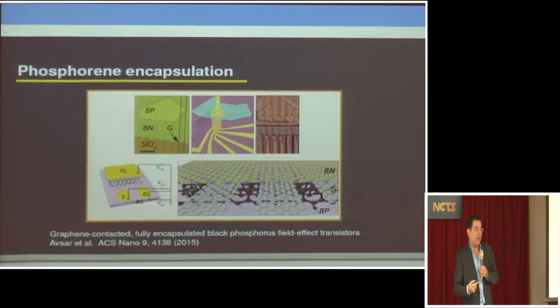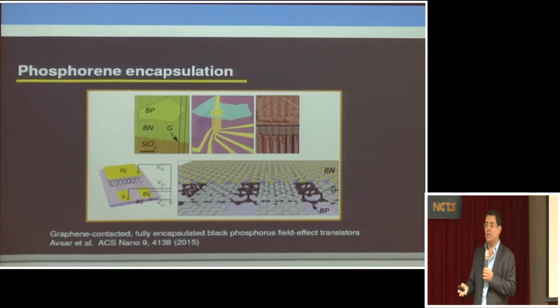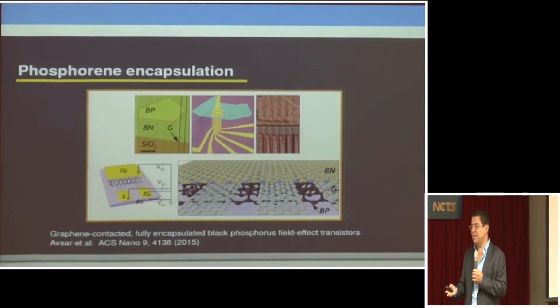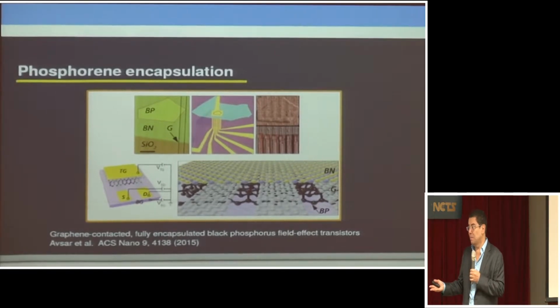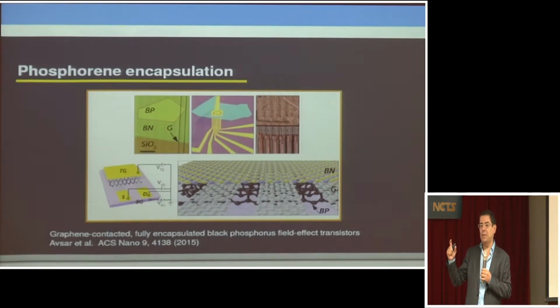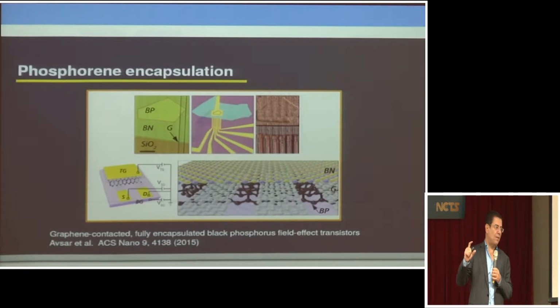So how did we manage to control it? I told you, graphene doesn't oxidize. So the solution is essentially you just cover the surface of phosphorene with graphene. This is called encapsulation. Actually, we don't use graphene most of the time, only when we want to make electrical contact. What we use is a different material called boron nitride, which is a wide bandgap semiconductor, 5 electron volt gap, and also very stable in air.